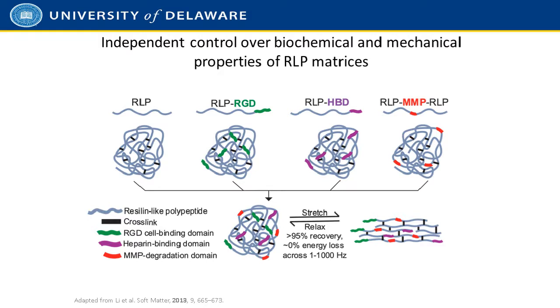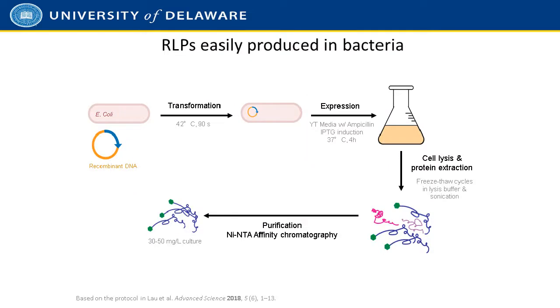We make these genetically, which allows us to incorporate not only the structural features of the RLP, as is shown in a very simple schematic on the far left of this slide, but also different bioactive domains. So we can incorporate cell binding domains, as shown in green, heparin binding domains, as shown in purple, and then MMP, or matrix metalloproteinase, so enzyme degradable domains as well, so that these materials can be degraded once they're deployed in vivo. We make them in bacteria.